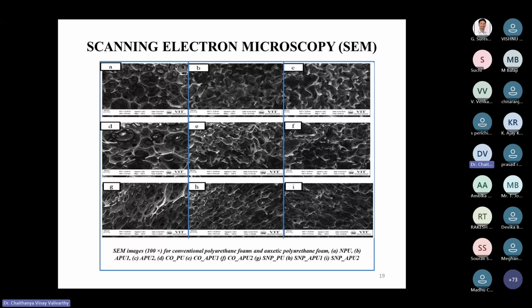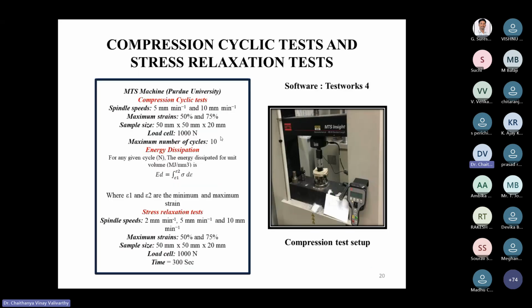So this phenomenon is called the buckling phenomenon. It is common in all foams, like CO and SNP foams. Now, on these foams we have conducted cyclic compression tests and also stress relaxation tests, which are creep. We used the MTS machine here and calculated the energy dissipation values from these studies. The standard for this is ASTM D3574, which is a standard for normal foams.